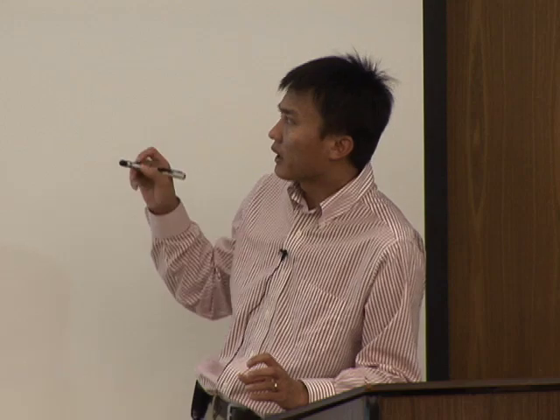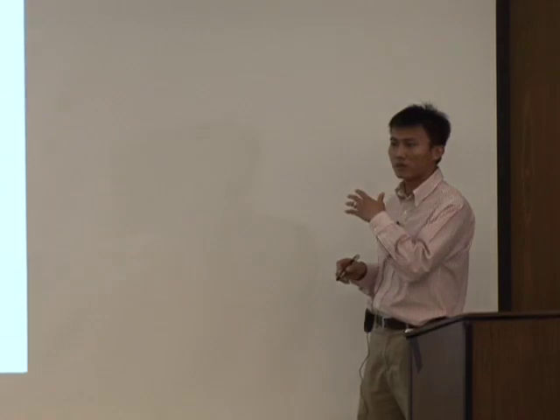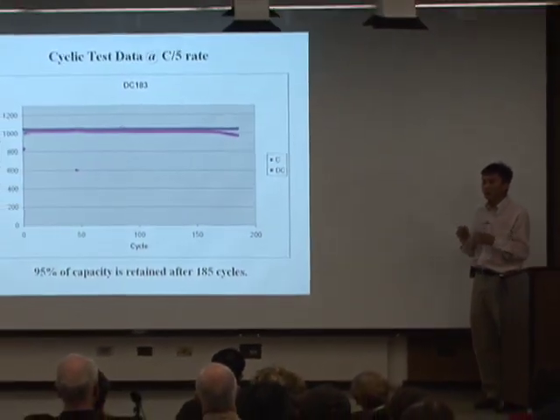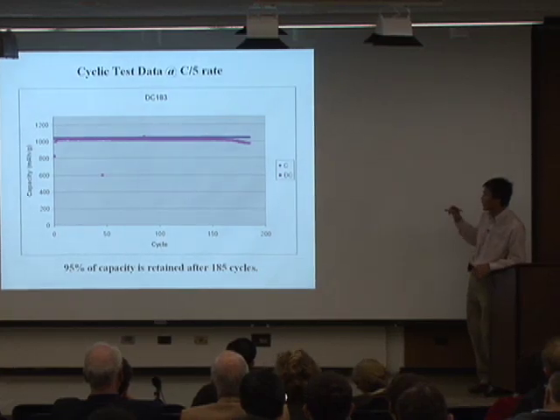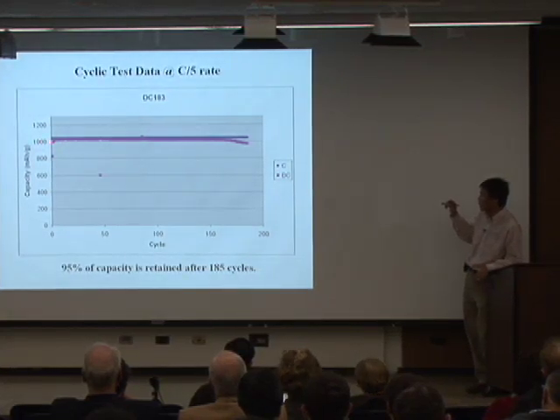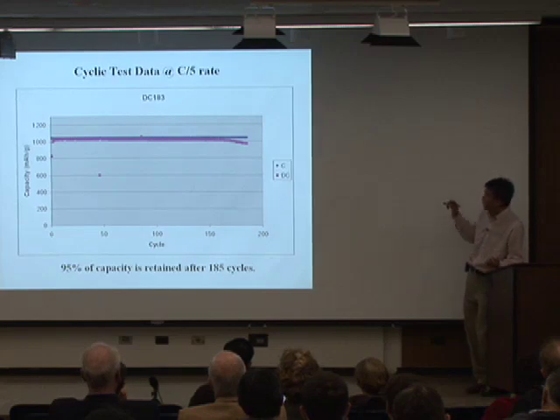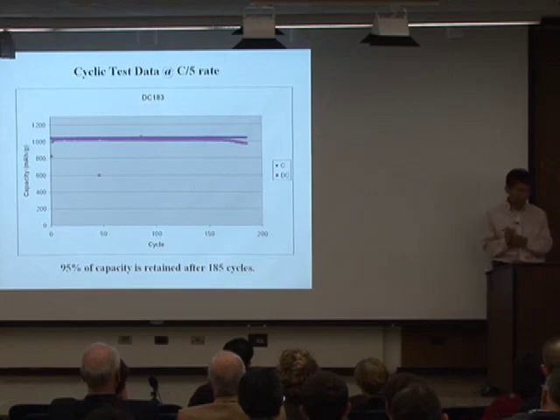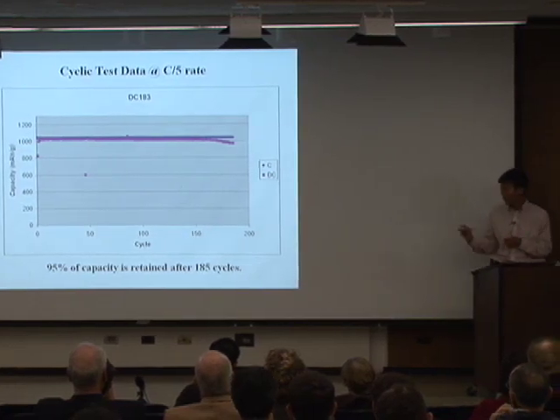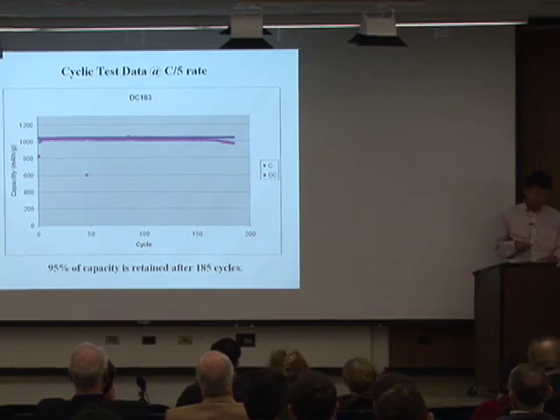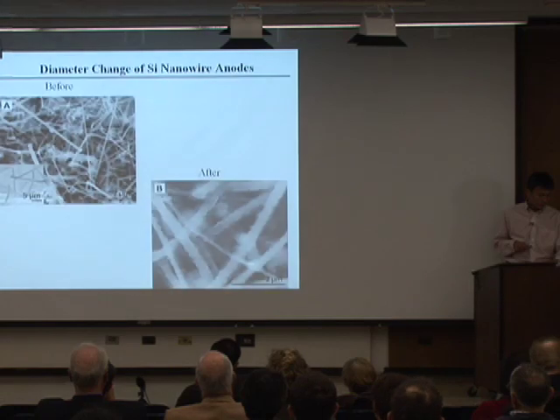Well, how many cycles can we run now? It looks like these nanowires are robust enough to allow us to go for many, many cycles. But we didn't push the nanowires that hard. If you push them very hard, if you want to charge 4,000 milliamp, that's their full capacity, you are going to break them after tens of cycles. So we decided to try about 1,000. 1,000 is already 3 times that of carbon. You can run close to 200 cycles with very, very little fading of capacity. You keep 95% of capacity.